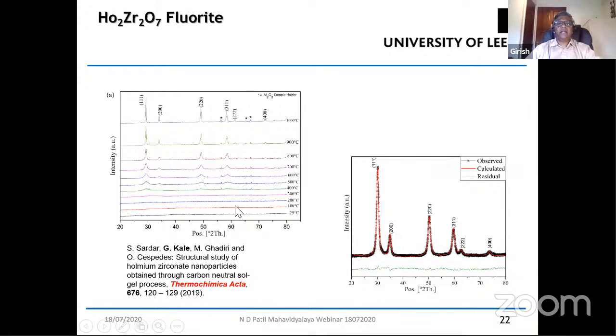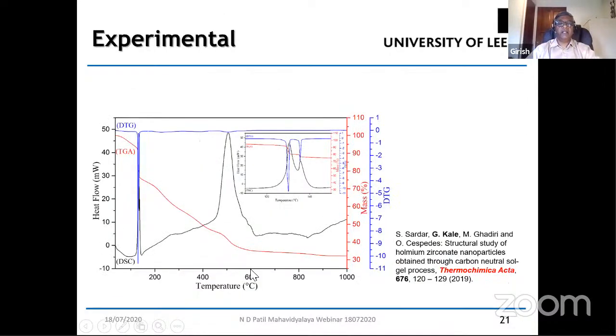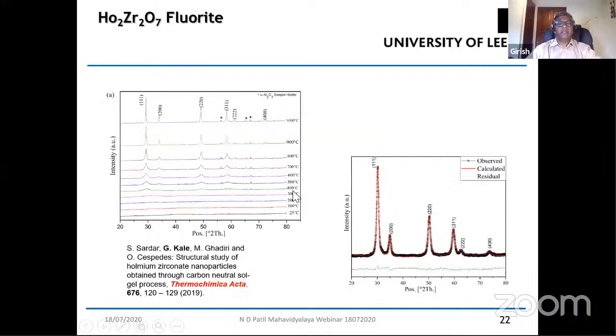And what we find is that, again, this corroborates very well with the data that we got in the DSC TGA diagram, that the nanoparticles have a fluorite structure, this holmium zirconate. You can see that the peaks start appearing almost at around 400 to 450 degrees Celsius. And at 500, you can see that the peaks are very clearly visible. The peaks are very broad because of the nature of the particle itself. Because they are very tiny particles, nanoparticles, you expect the X-ray diffraction peaks to be broad.